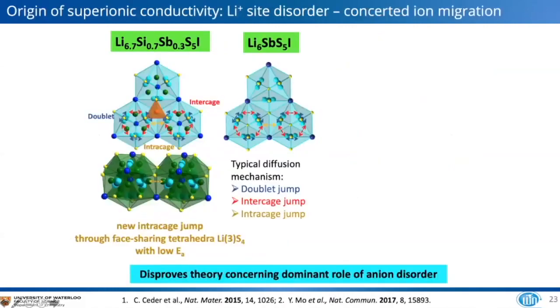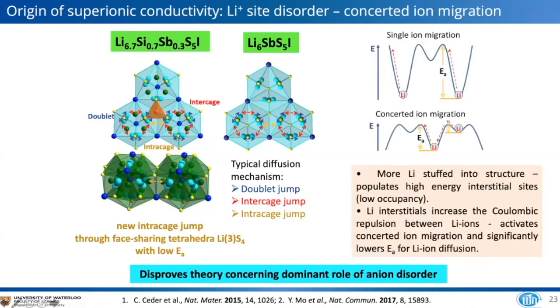So the reason for this increase in conductivity is that we have these additional sites which lie between these Frank-Kasper polyhedra. These are the cages that are shown here. And so whereas we would normally have these jumps within the Frank-Kasper polyhedra and also some intercage jumps, the addition of these new sites through face-sharing tetrahedra, it's a little hard to see, enable this intracage pathway.